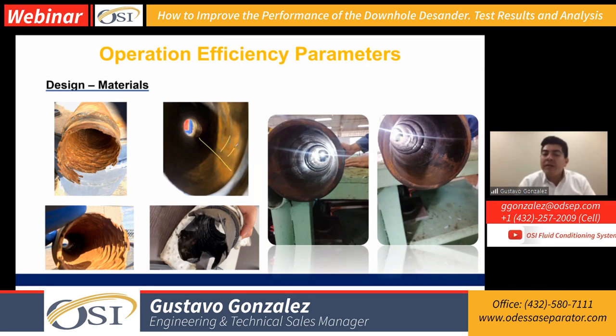But one of the things we see is the tailpipe underneath it, or the mud joint where the sand was stored, started creating too much centrifugal force at the end of the connection of the collar. We actually cut that tailpipe, because the drawdown generated through the system was higher, pushing that centrifugal force around 2.5 feet, and that's why we start to see the damage in the tailpipe.